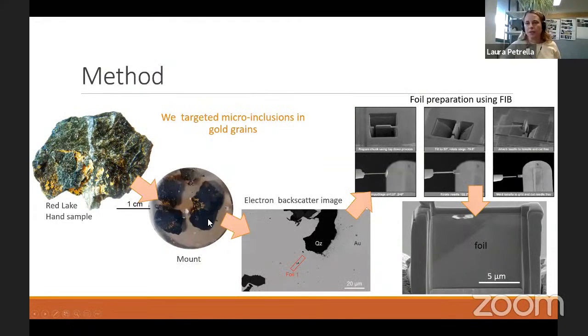This is the method that we used. I used the example of our Red Lake sample. We made a mount out of this sample, and we looked at it with the SEM. At this stage, what we did is target inclusions in the gold. The light gray that you see on this backscatter image is a gold grain, and some of these dark spots in the gold are inclusions. So we selected interesting inclusions that we extracted to look at with the TEM.